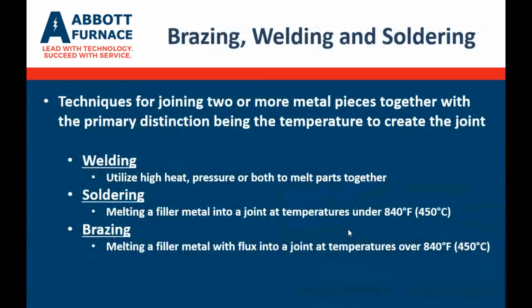So brazing, welding, and soldering are all ways to join metals together. Welding utilizes high heat or pressure to melt parts together. The difference between soldering and brazing, just for definition, is that soldering is melting a filler metal into a joint at temperatures under 840 degrees Fahrenheit or 450 C, while brazing is melting a filler metal with flux into a joint at temperatures over 840 degrees F. So that generally is the difference between soldering and brazing.